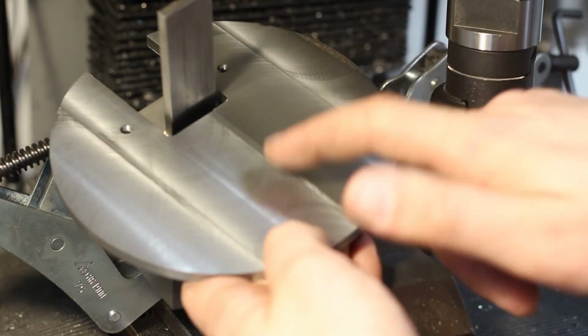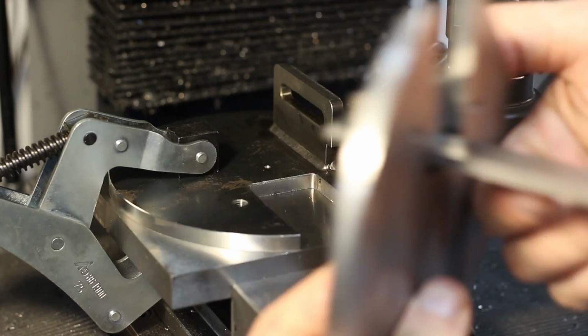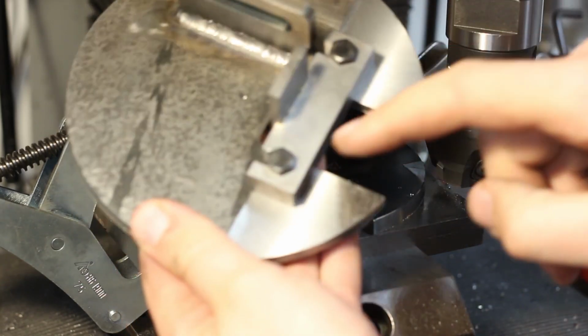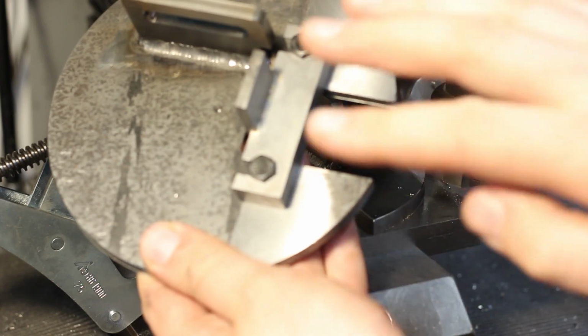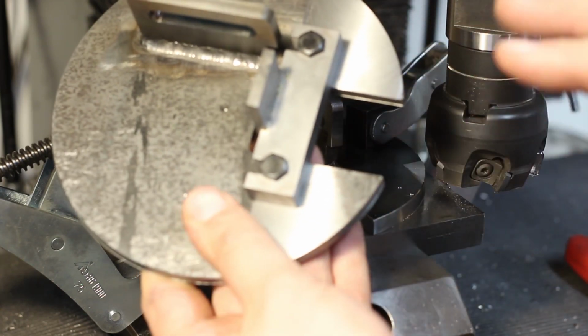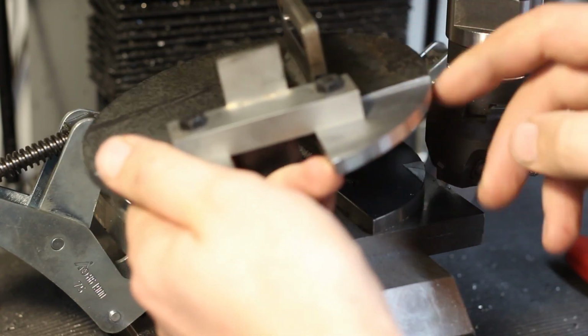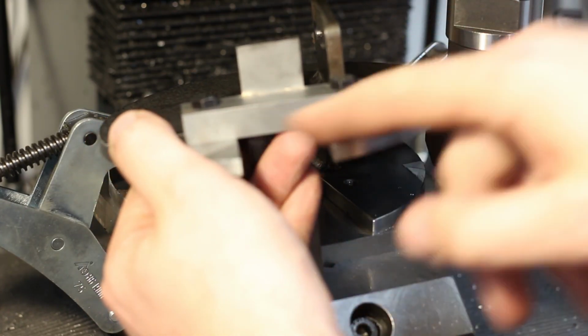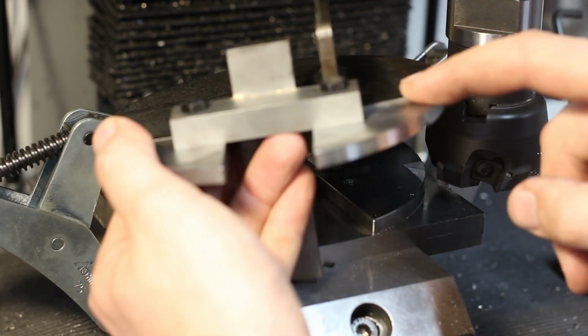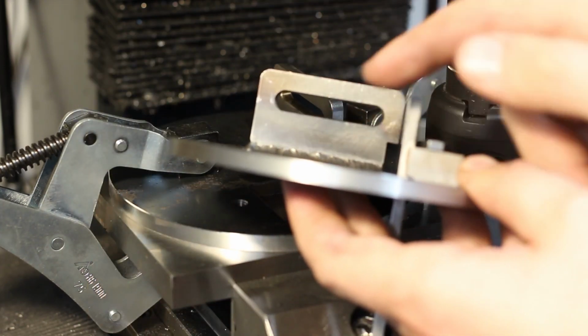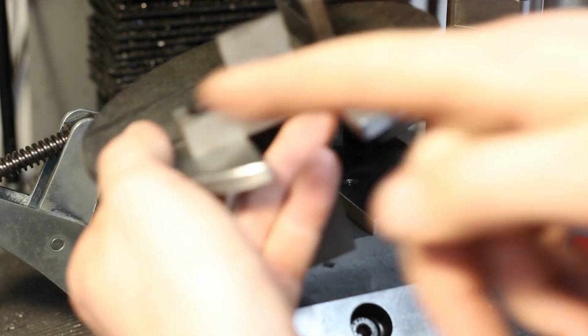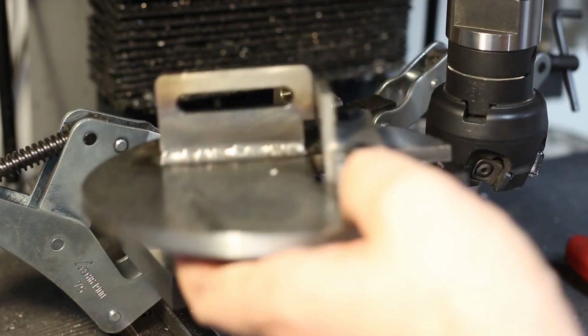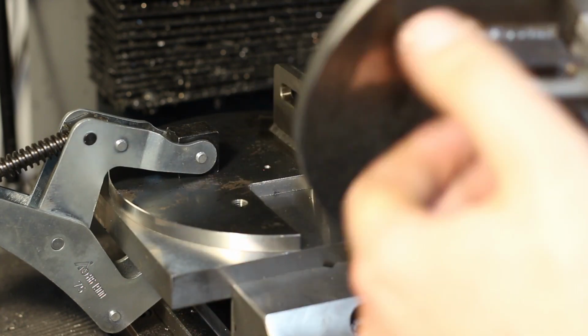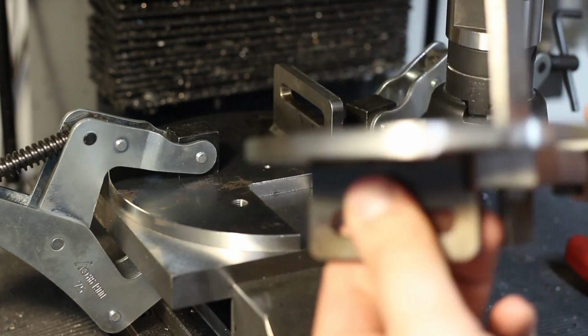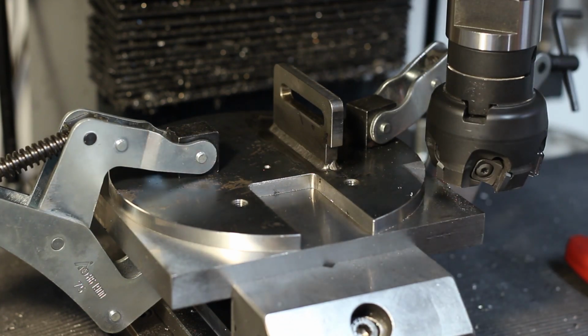So after face milling the front, the tabletop, I flipped it around and I'm also milling the mounting surface where the belt guide bolts to. So everything is in the end square, even if I have significant distortion from welding. This thing bowed by roughly 1 millimeter by the huge amount of weld metal and heat input I put into it. So this plate potato chipped seriously on me. But that's not a problem. There's a lot of material on it and I can machine it true and square in every aspect that I need.